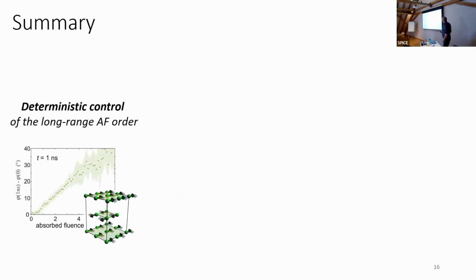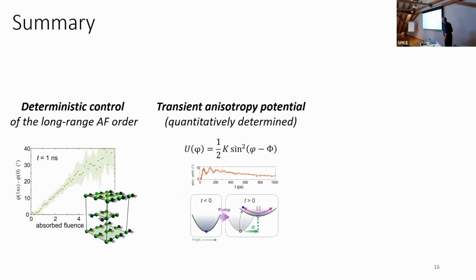Right, so I'm going to summarize this very short part by saying what I did and didn't say. So this is what I just showed you. And what I didn't show you is that through this wiggle, and we solve the spin structure for every delay, we can also reconstruct the local anisotropy potential of a spin in real units of energy and angle.